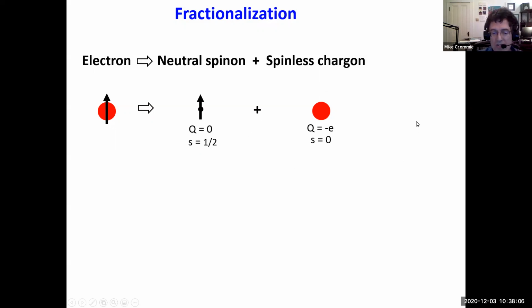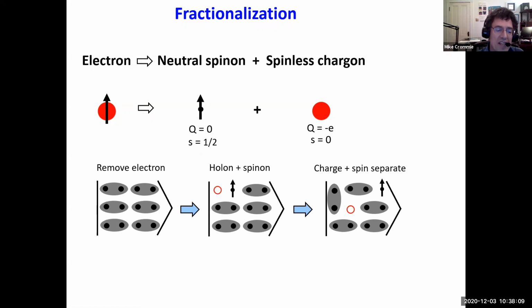One way to think of that intuitively is to consider this resonating valence bond state that I show down here below. If I pluck out an electron, then I leave behind an unpaired spin and a holon, a hole. Now those two, the holon and the spinon, can migrate away. If you start rearranging the bonds and moving electrons around, you can see how they separate and move away. And that's a way of thinking that the electron is breaking apart into these two other types of particles.